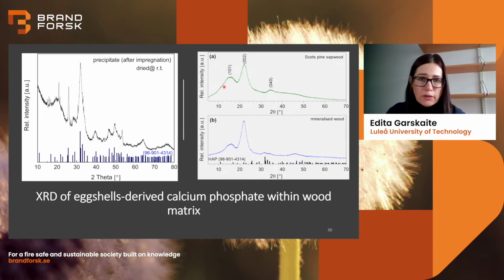Because it's overlapping and we get very strong reflections from the cellulose, we thought it's valuable to take those powders and also record them. What we see is that the main peaks correspond to hydroxyapatite, and the main reflections of the reference also give changes in the region where it overlaps with cellulose. Doing some other complementary analysis as well, we decided that we have a low crystallinity hydroxyapatite. So probably by annealing at high temperatures, we will get a very high crystallinity hydroxyapatite.